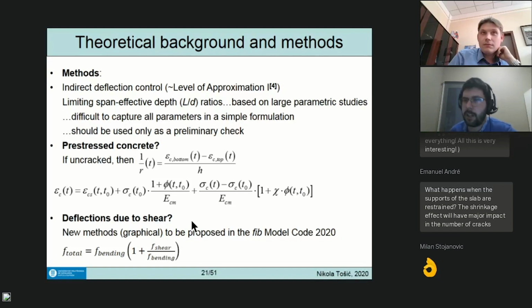For example, if I recall well, in the one that was done for the current Eurocode, a creep coefficient of 2 was assumed, a shrinkage strain of 0.4, and a ratio of quasi-permanent to design load of 0.5, whereas in buildings it usually comes out as 0.62, for example. This means a bigger impact on the L/D ratios, so there were changes necessary there. The recommendation is to use it as a preliminary check to get to your slab depth, but then use one of these simplified methods to do a full calculation of deflections.